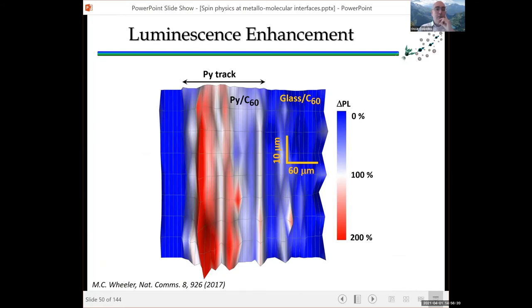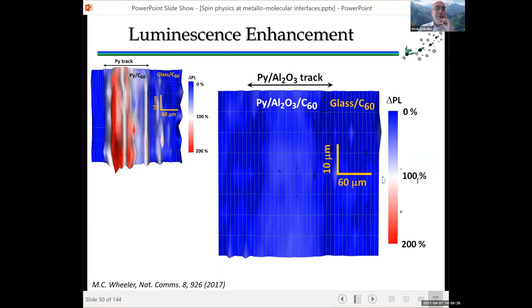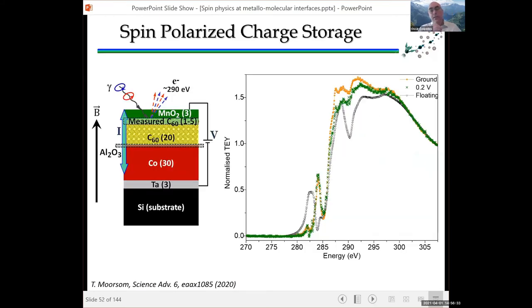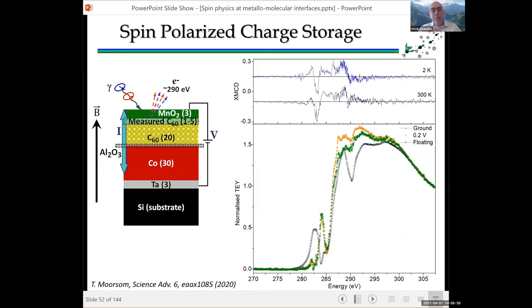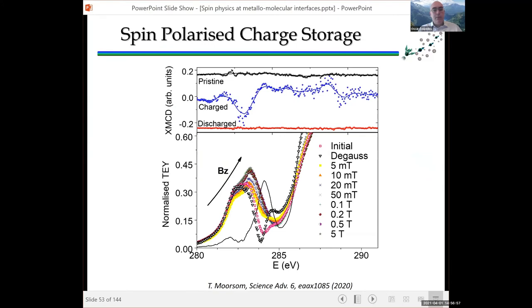And the last thing I really want to point out is the effect of spin storage, where if you apply a current to a C60 metal oxide interface, you can trap a charge at the metal oxide molecular interface, like a capacitor, and that charge is spin polarized. You can see that it's spin polarized by doing XMCD measurements. And that charge remains stored and spin polarized at that interface for macroscopic time scales. So you can see those effects for minutes or even hours. And again, if anybody's interested, we can have a look in more detail.